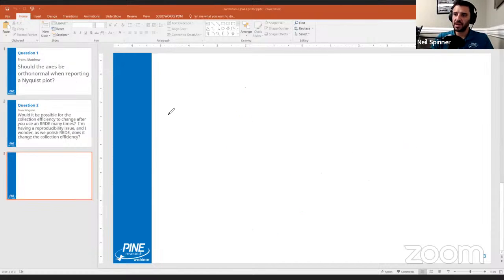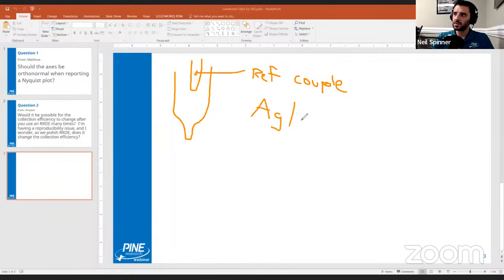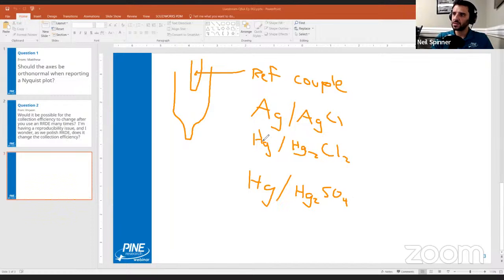Now, the reference electrode is where it really does matter. So there's a lot of considerations with respect to the reference electrode. The first and most obvious one is that reference electrodes typically have something inside here. This is where the reference electrode couple is, basically what determines its potential. So this could be silver chloride, could be calomel, which is mercury chloride. It could be mercury sulfate. These are some of the most popular ones. The alkaline one of choice is usually mercury oxide.